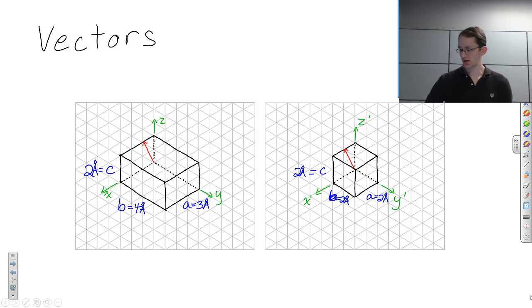When we start trying to describe this vector, we can break it into components in the different directions. This orthorhombic one, the component in the x direction is that long. The way we describe this is we say that distance would be 1 angstrom. And in relation to the side A, it is equal to one third of the side A. And then the z component, this component of that vector, is 2 angstroms. And if we compare it to the side C, we'd see that it is one times that side C.